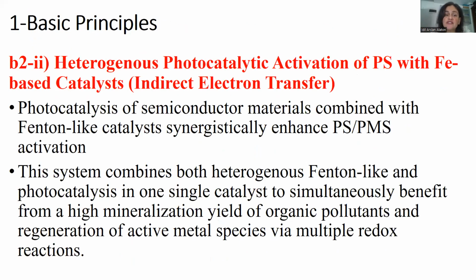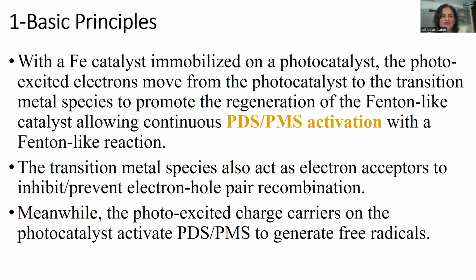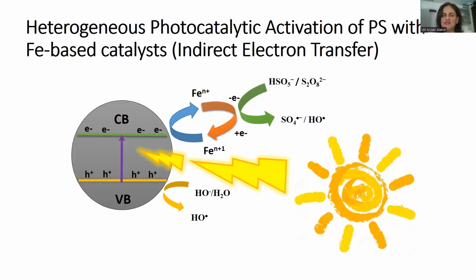Then the heterogeneous photocatalytic type, which involves indirect electron transfer, because sometimes we can also combine Fenton-like catalysts with photocatalysis, incorporated in the photocatalyst by doping or other methods. This system combines heterogeneous Fenton-like reactions with photocatalysis in one single catalyst. So here we have really high mineralization yields, and the iron, for example, iron can be the metal, is also involved. So the immobilized iron catalyst promotes a Fenton-like reaction at the same time. And it also scavenges or combines with the conduction band electrons. In this way, iron can be recycled back, so it is reduced to its original state and continues the Fenton-like reaction. Here it's maybe seen in a clear way.